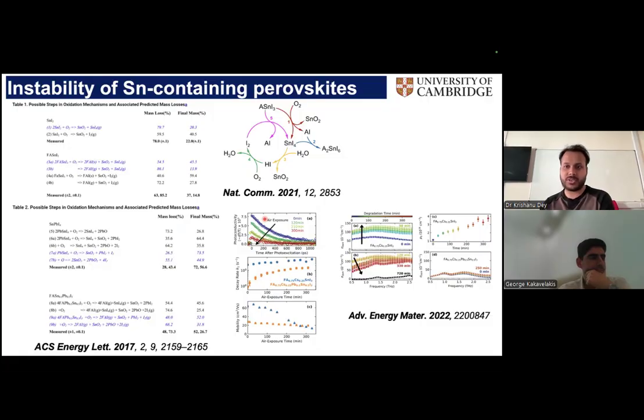So as soon as it sees some oxygen or is exposed to air, it tends to oxidize pretty quickly, and there are different ways of degradation of these materials, which are already discussed quite extensively in the literature. These publications talk about them, and when they degrade, they also affect the optoelectronic properties of these materials. So it's very hard to work with these materials if you can't control the conditions of your glove box, let's say, and your measurement, right.